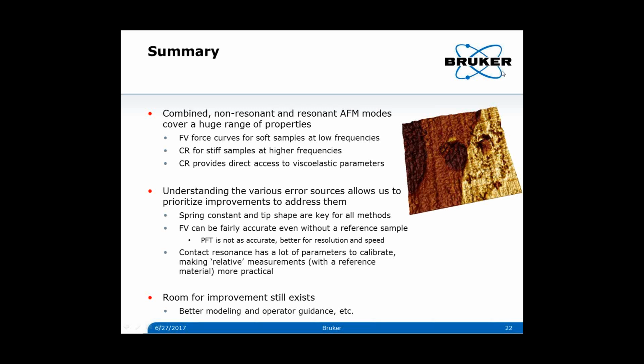Very good, thank you, Dalia. And Bede, in the sample with laser vibrometer calibrated tips, is the deflection sensitivity still being calibrated by the operator? Yes, the deflection sensitivity is calibrated by the operator, but we have a guided method that basically steps the user through that. So it's almost automatic, but it does use the calibration of the AFM, the piezo, to calibrate that deflection sensitivity there.